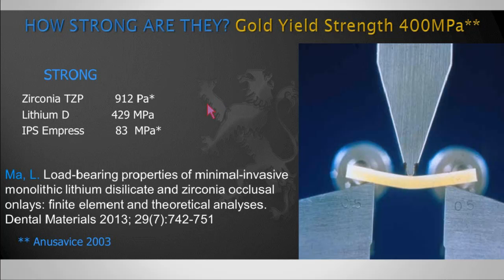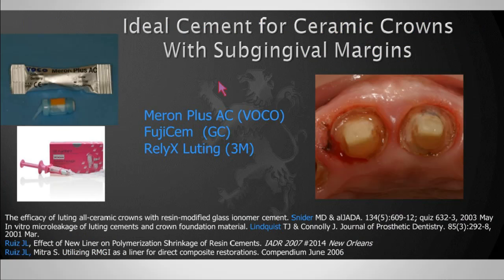Lithium disilicate, on the other hand, is about half that strength. And if you start looking into materials like Empress or feldspathic porcelains, you're usually going to be below 100 megapascals. So if you have a situation like this, and you're going to be struggling to control the bleeding, wouldn't it be easier to use a cement that is more forgiving to contamination? Of course. So then we would consider materials like Meron Plus, which is a wonderful cement, or Fuji Cem or Relyx Luting.